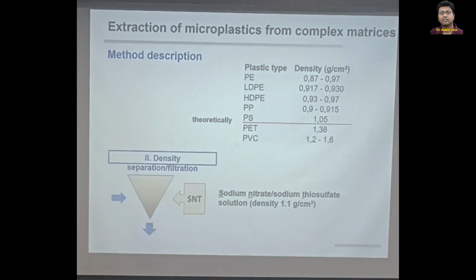What is this density separation? You know, the different plastics, they have different densities. Okay? And I can, for example, separate the very heavy plastics from the not so heavy plastics using a solution that has a defined density. Okay? In this case, we use the sodium nitrate, sodium thiosulfate solution, that the density, the theoretical density, allows us to separate between the very heavy plastics from the lighter plastics.